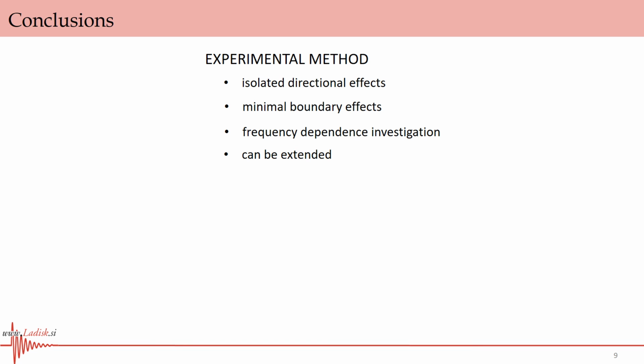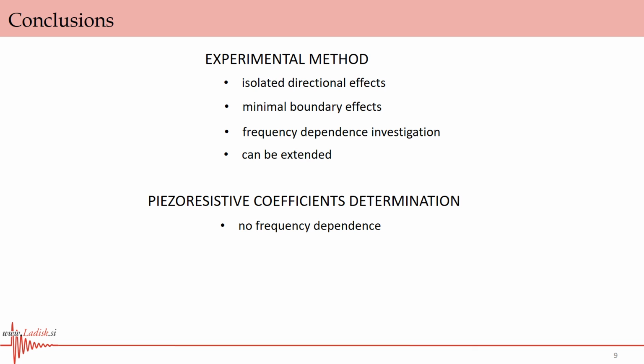The developed procedure can be extended to the determination of remaining coefficients by applying electrodes perpendicular to mechanical excitation direction. However, the influence of boundary effects on the identification of piezoresistive coefficients should be investigated in some more detail. Through the evaluation of applicability of the method, it was observed that piezoresistive coefficients do not exhibit any frequency dependence in examined frequency region, and that higher piezoresistive coefficients are observed in the direction perpendicular to material deposition direction.